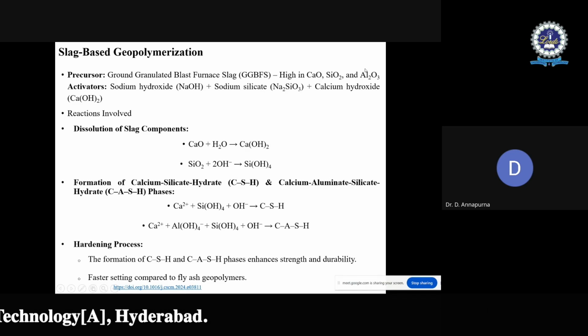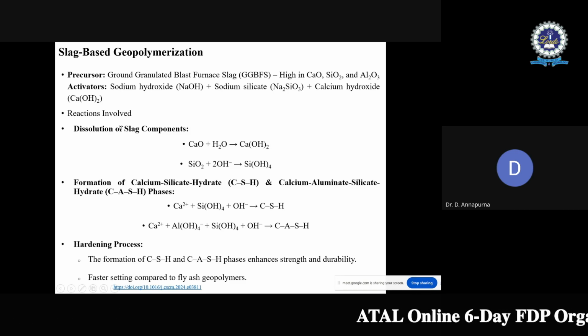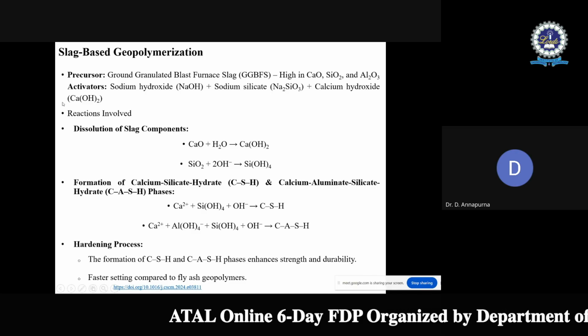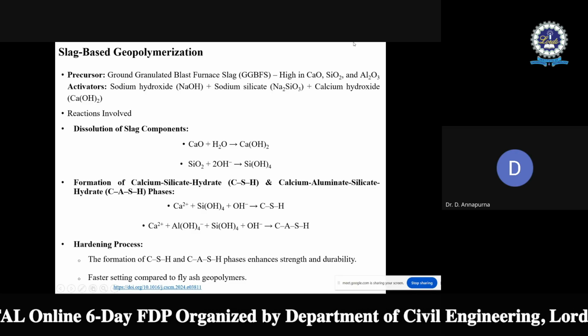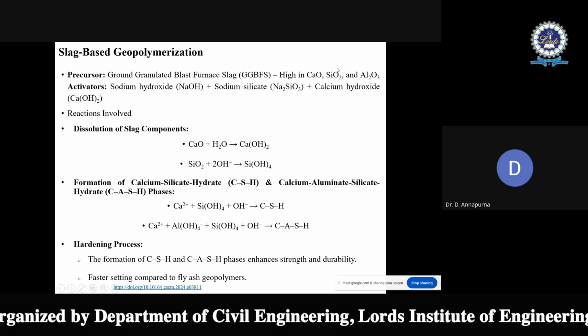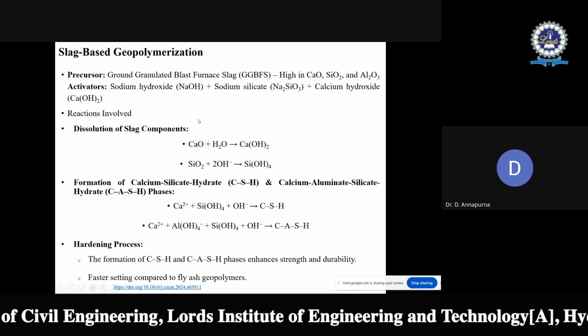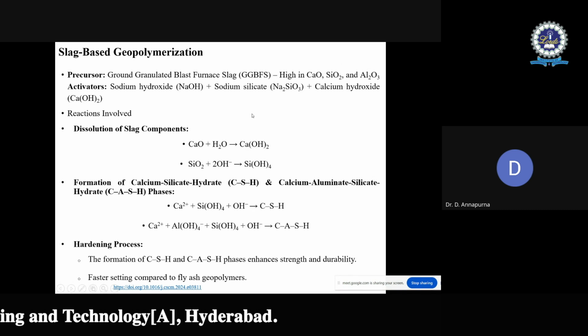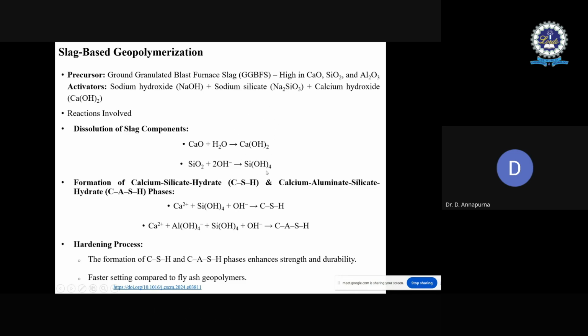So there will be a slight change in the chemistry of the geopolymerization process. So what are the reactions involved? First, dissolution of the slag compound. I said here that it is rich in calcium and silica also. So calcium and silica will be dissolved and converted into this particular form, calcium hydroxide and silica hydroxide.